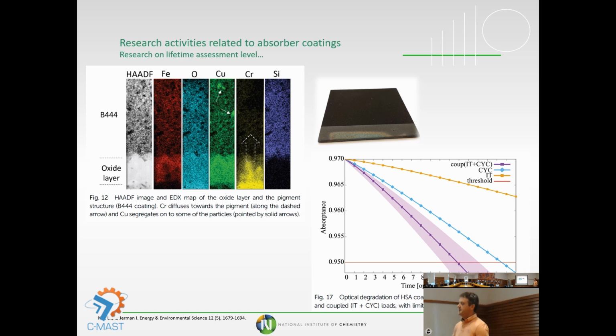So everything was then used for calculation. I don't plan to go into detail today on how we produce the model, but I will describe the results. As you can see, we couple isothermal load with cyclic load. In addition, we evaluate what happens with the coatings if we cycle them at different speeds from room temperature up to 800. So we made a few thousand cycles in 2-3 months. We heat up, we cool down, we spray water inside the oven, and again we repeat.